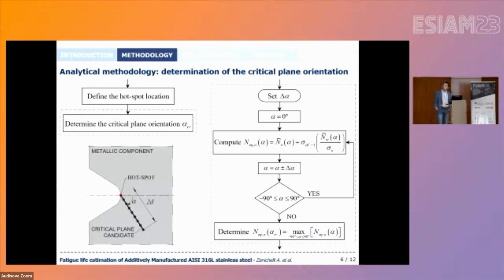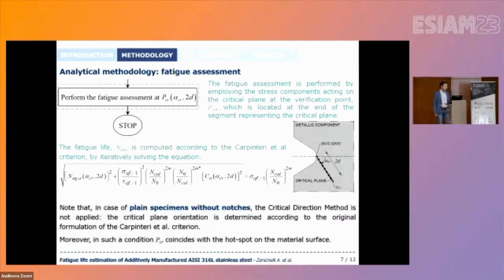Well, once the critical plane orientation has been defined, the fatigue assessment follows, and it is performed by employing the stress components acting on the critical plane itself at the verification point P critical, which is located here at the end of the segment representing the critical plane, that is, at a distance from the hotspot equal to twice d. And the fatigue life is computed according to the Carpinteri criterion by iteratively solving the equation shown in the slide. So finally, it is important to highlight that in case of plain specimens without notches, the critical direction method is not applied. As a matter of fact, the critical plane orientation in this case is determined according to the original formulation of the Carpinteri criterion. And moreover, the verification point coincides with the hotspot on the material surface.